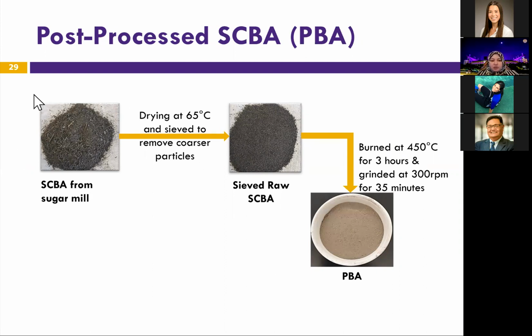This is what the sugarcane from the mill looked like. We dry it at 65 degrees and then sieve it. And by doing that, we remove the coarse particles and you get what we call raw sugarcane bagasse ash. This is what we used as a sand replacement. If we further burned the raw bagasse ash at 450 Celsius for 3 hours and grinded it at 300 RPM for 35 minutes, we get what we call processed bagasse ash. And this is what we use as cement replacement.